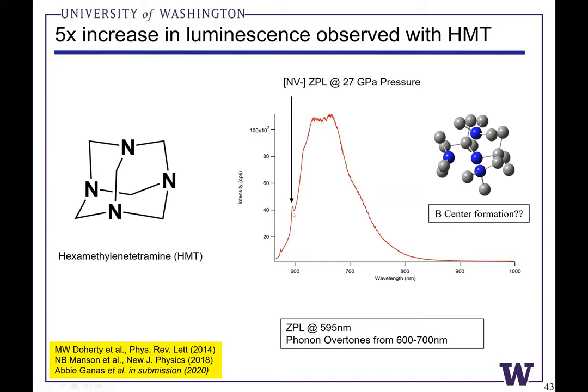Abby also has some really nice recent data on the pressure-dependent shift. Abby's been able to observe the negatively charged nitrogen vacancy center forming in these diamonds. And at high pressures, Abby's been able to make pressure-dependent zero phonon line measurements of these materials, and they correlate really nicely with previous reports of the pressure-dependent shift. It's about 5.75 millielectronvolts per GPa of a pressure-dependent shift, which Abby is also seeing in these diamonds she's made.